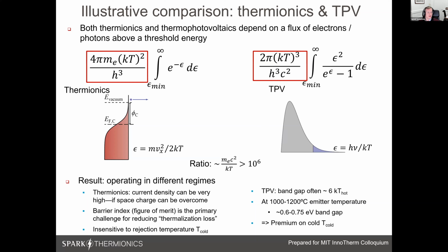In contrast, in thermionics, as long as you can get them across the band gap, we have more electrons than we know what to do with. So the space charge is the critical thing to overcome. And then that barrier index tells you, for these electrons, of the heat that they're carrying from the cathode of that voltage, what fraction is actually converted into useful power. And so this barrier index is a primary challenge for reducing the thermalization loss of electrons coming from vacuum and then thermalizing at the Fermi level.